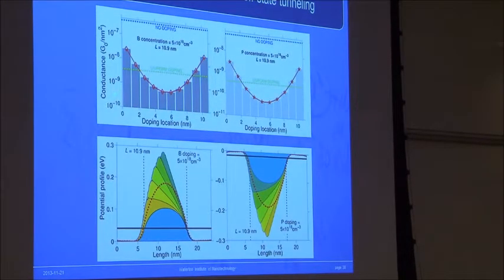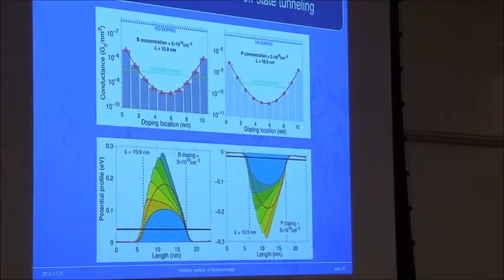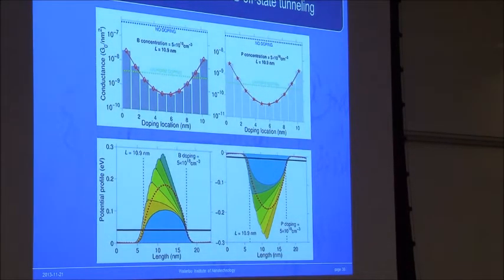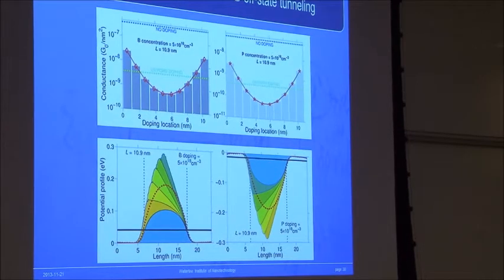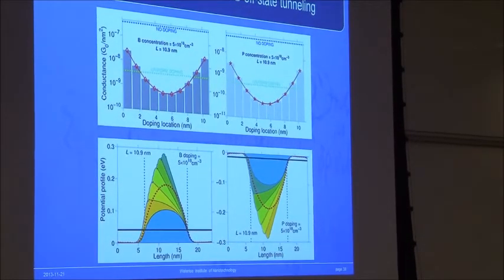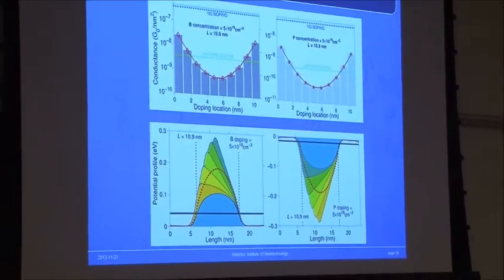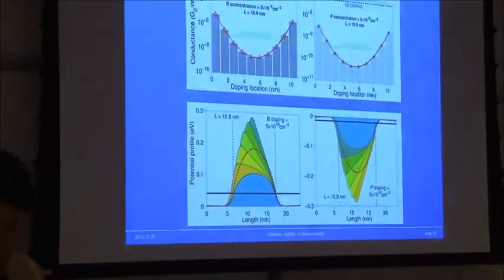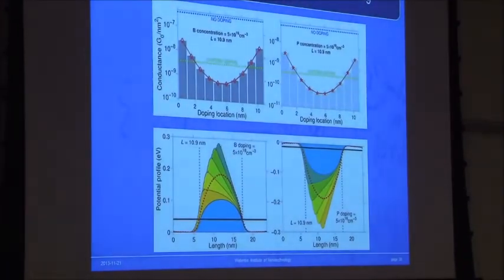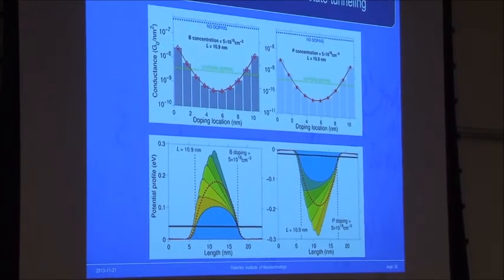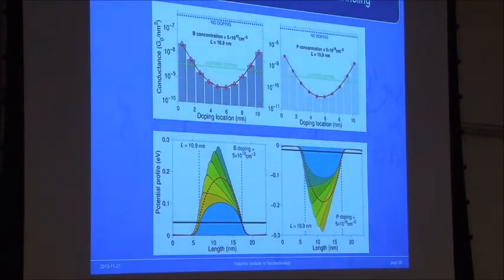So he calculates the leakage conductance as a function of where you dope along a channel of 10, 11 nanometers. If you dope in the middle, your conductance is much smaller. So actually you can suppress the leakage current by a factor of 40 or so. This is quite impressive, okay, for both N and P doping. If you uniformly dope the system like what we usually assume, then you get this tunneling conductance, which is much higher than this non-uniform doping. But if you dope in the wrong place, suppose you dope at the contact, then you are even worse. Okay, your leakage is much higher.